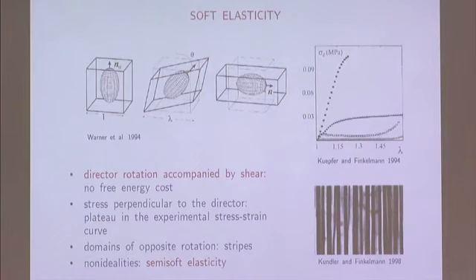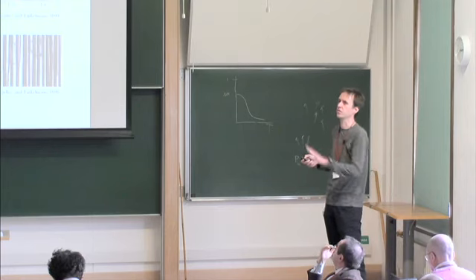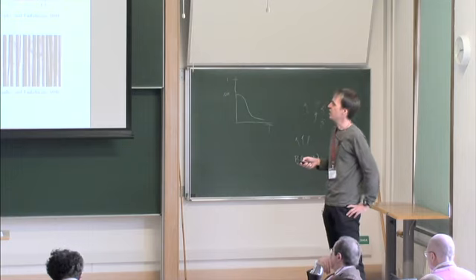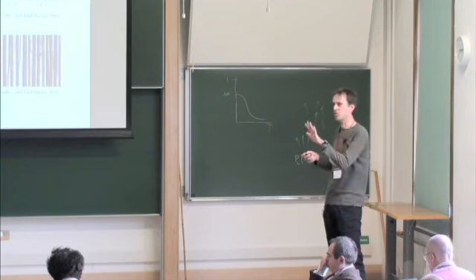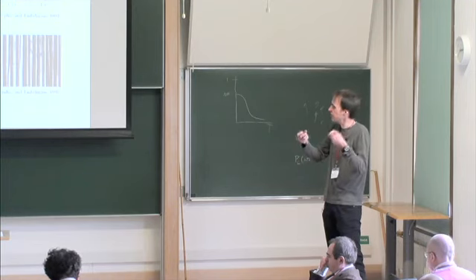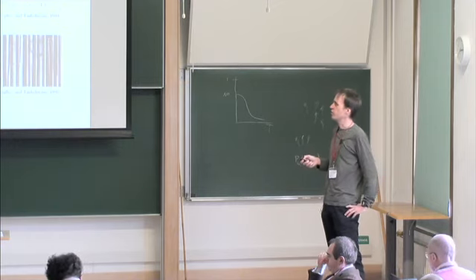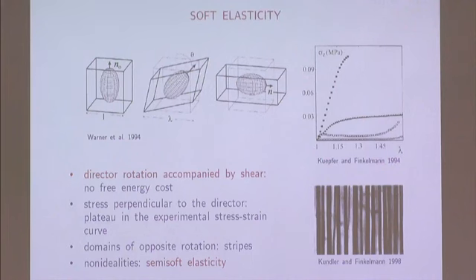Now, you can see that here in this curve there is some threshold. Before this rotation takes place, there is a well visible threshold, and this is typically because your system has some imprinted or residual anisotropy or some easy axis, like our systems do, also our simulated systems. So you have some kind of internal field, and when you apply some external, let's say, mechanical field or some other field perpendicular to your existing field, first your existing field has to be overcome to allow for the director rotation, and this is what's called semi-soft elasticity.